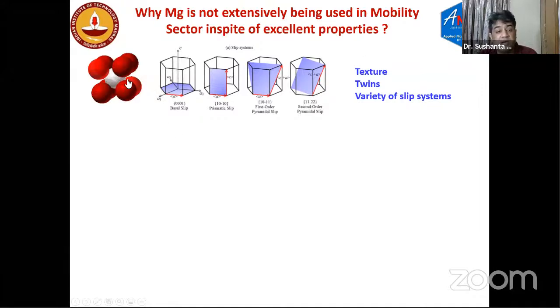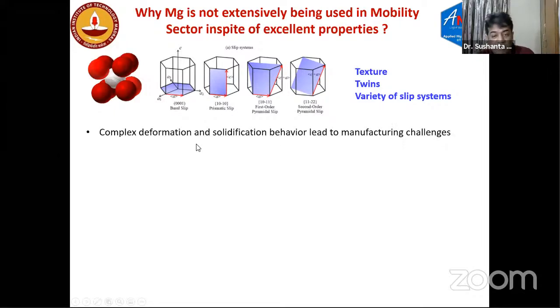It is because magnesium has the HCP crystal structure. Because of this HCP crystal structure, whenever you want to do plastic deformation, to develop a rod component or in the form of sheet or extruded product or anything, the deformation phenomena becomes complex, because twins will form, texture will form, and there is a variety of slip systems. It has basal slip system, non-basal slip system, pyramidal slip systems, and it is a complex microstructure slip deformation to understand.